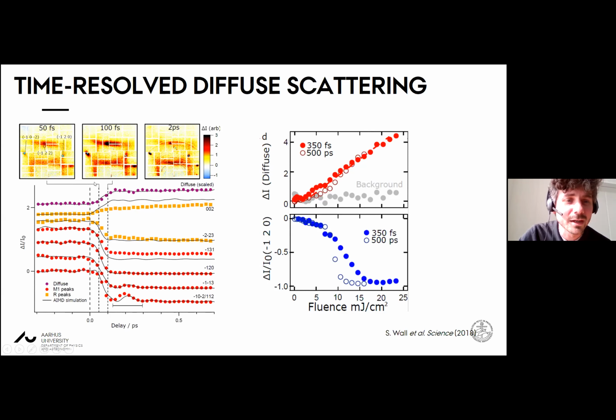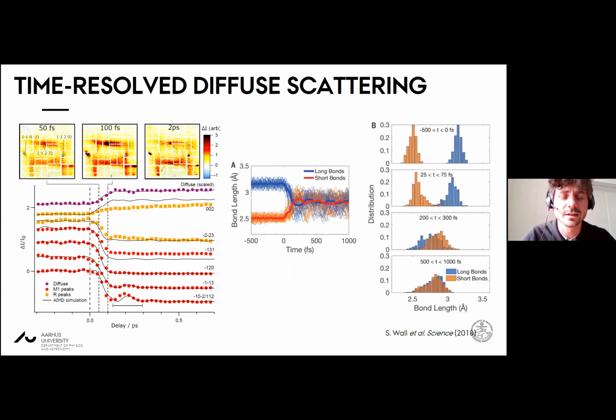The important point here is that we find that all Bragg peak and diffuse scattering changes happen at the same time. We see that the system has the same threshold as observed in optical experiments. And this tells us that the system is disordering. From the MD, we can visualize what's going on here. I'm plotting now bond length instead of atomic position, and we have a short and a long bond due to the dimerization. We see that this nearly instantaneously collapses onto a single bond. Here are the distributions. We have an initial thermal distribution of the bonds to start with, and they very quickly collapse onto a single distribution. We can think of this as a disordering, or high entropy, process, because after a few hundred femtoseconds we can no longer decide if an atom started off in a short or a long bond. So this system has lost all sense of order.